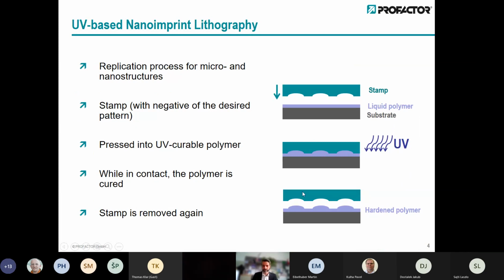Just very, very briefly, what nanoimprint lithography is. You take a stamp which contains the negative features you want to have on your surface. You press your stamp into a liquid polymer which is coated on your substrate. The polymer fills the cavities. You do some UV curing, in our case, to harden the polymer, and you can remove the stamp and you have replicated those structures. So it's a replication process for nanostructures.